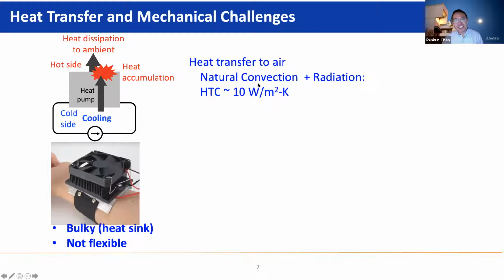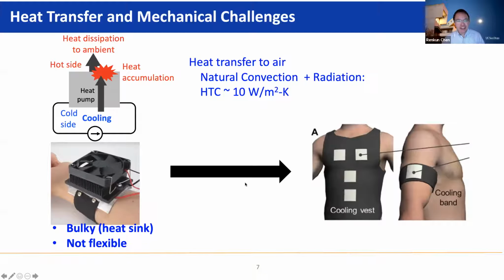And if you don't have a heat sink, then we are talking about natural convection and radiation heat transfer. These are the only two heat transfer modes from the hot side of the device to the air. And the combined heat transfer coefficient, HTC, of these two modes is at best around 10 or maybe 12, 15 watt per meter square Kelvin for natural convection and radiation. So that makes it really challenging to dissipate the heat to the environment without a bulky heat sink. So that's our goal. We want to make a compact and less bulky thermoelectric device, meaning we want to get rid of this bulky heat sink. And also we want to make the device itself flexible.